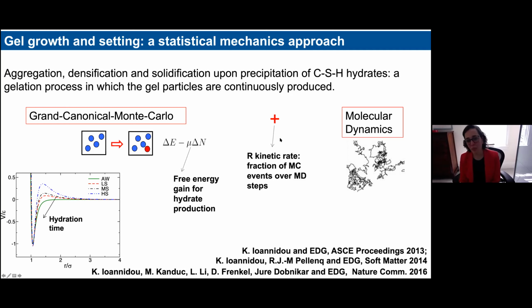There is just one thing that I would like to add. This combination of grand canonical Monte Carlo and molecular dynamics allows us to change the rate of this precipitation, and to study how this can drive the formation of the structures more or less far from equilibrium, compared to what we would obtain with just a molecular dynamics simulation, as you would do for a normal colloidal gel, where a certain amount of particles are present from the beginning and they just aggregate and gel depending on the interactions.